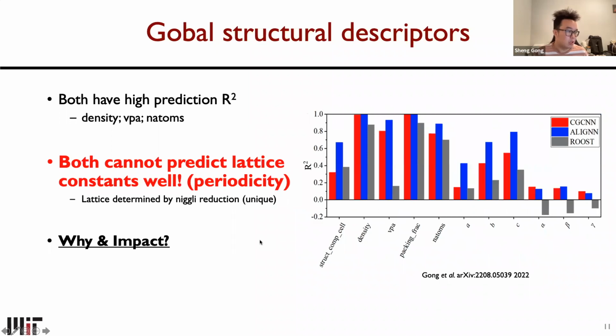And when it comes to global structure descriptors, we found something surprising. First of all, we found that both CGCNN and ALIGNN have high prediction R-squared score for some global properties like density, volume per atom, and the number of atoms in the unit cell. But we found that both cannot predict lattice constants well, which are the a, b, c and alpha, beta, gamma on the right of the figure. And these lattice constants actually describe the periodicity of crystal structure.